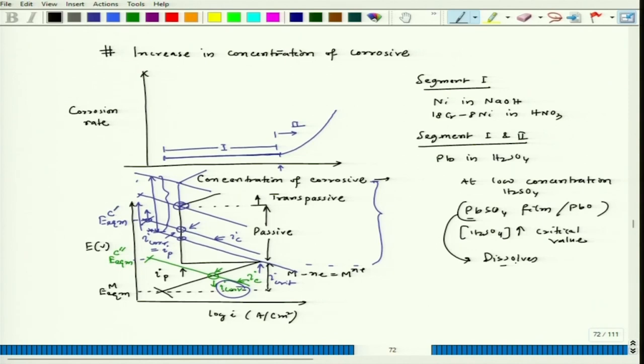So that means the bare metal surface is exposed, and the material corrosion rate further increases, and sometimes it becomes an exponential rise. That particular pattern is observed in the case of lead pipe. Let's say consider lead pipe carrying H2SO4. At a low concentration, it can maintain a low corrosion rate, but at a high concentration, definitely lead becomes highly soluble. Okay, corrosion rate further increases. So that's what these two patterns can be observed in the case of lead, starting from low concentration of H2SO4 to high concentration of H2SO4.